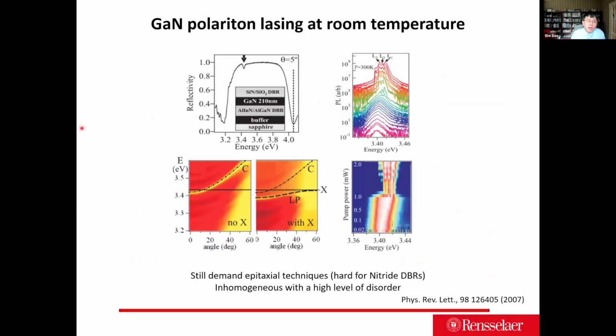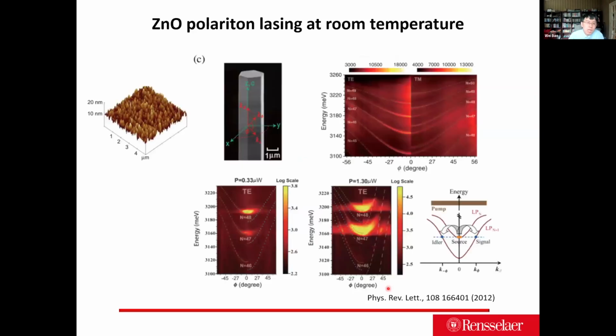Specifically, take gallium nitride, for example. Researchers demonstrated back in 2007 in a PRL paper, one year after the 2006 Nature paper on the cadmium telluride quantum well, that a gallium nitride bulk crystal integrated with DBR can run into polariton lasing. But from their experiment, you can see the linewidth of this material is really broad, and the Q factor of this cavity is really poor. That means nitride growth is still very hard for the DBR, and the quantum well structures are not ready, and gallium nitride tends to have a higher degree of inhomogeneity and disorder associated with that. So compared with gallium arsenide and cadmium telluride, people think it's okay for demonstrating polariton lasing at room temperature, but to study a lot of the polariton physics or Bose-Einstein condensate physics, this material is not so ideal.